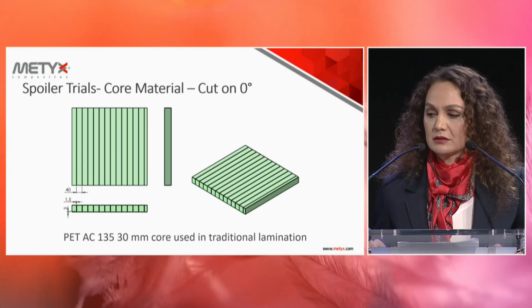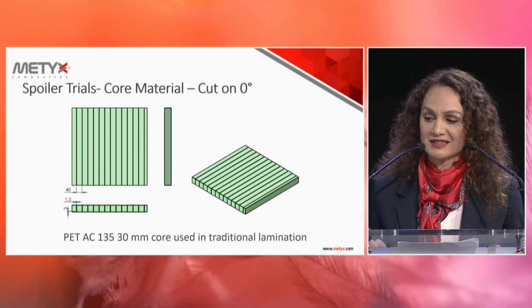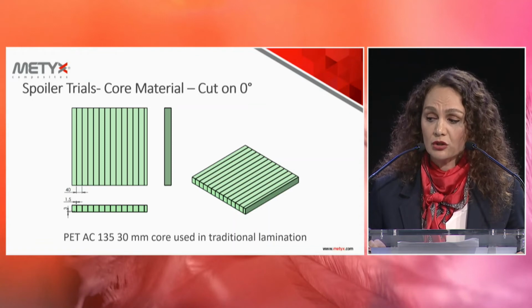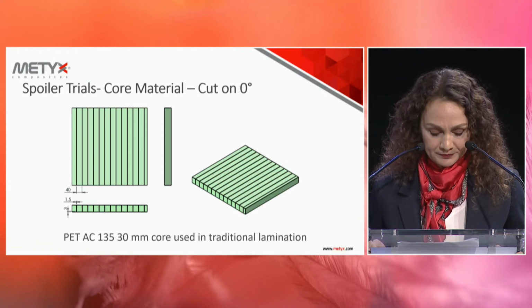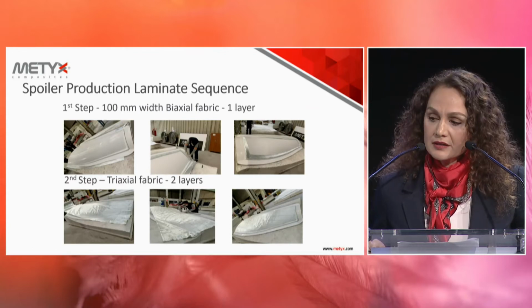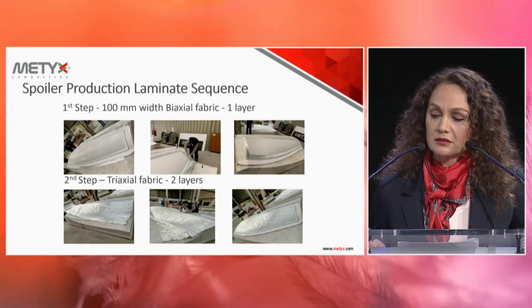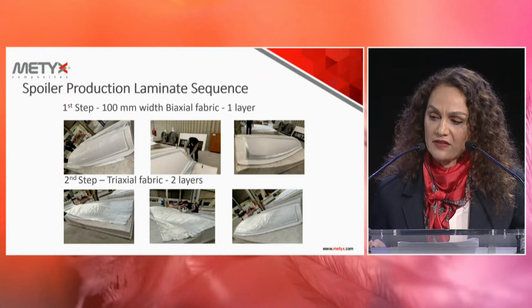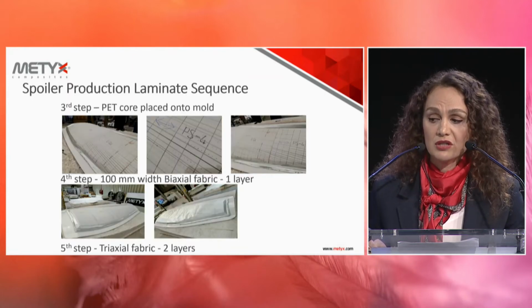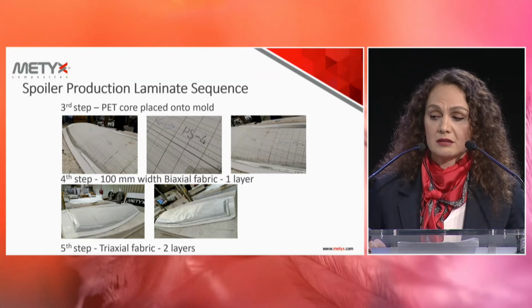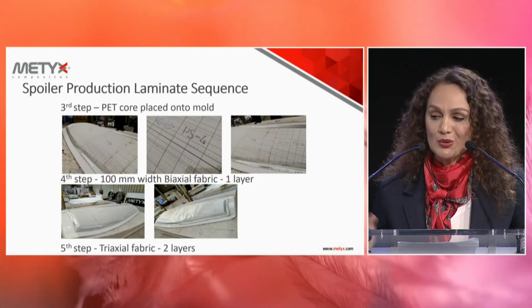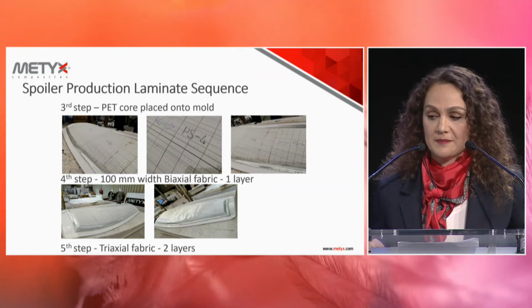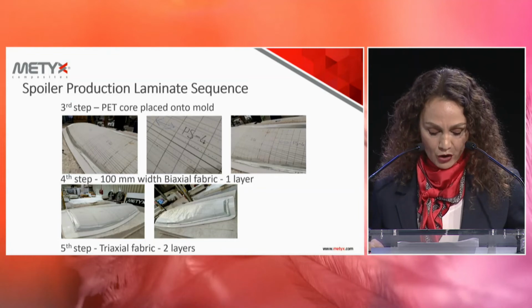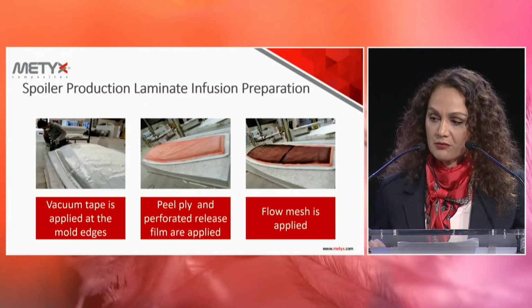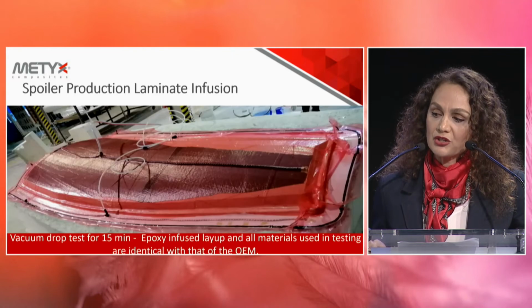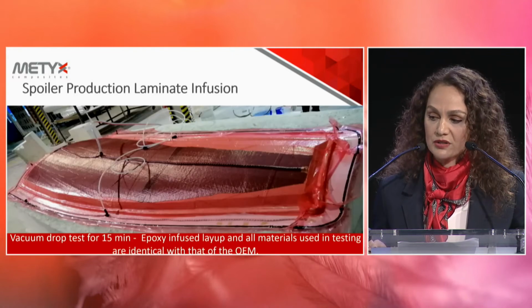So the other comparing core has the cuts in 0 direction. It has the grooves. So you can see the same laminate sequence in biaxial and triaxial fiber lay down. And then on the top 3 images, you can see the PET core. It has lots of grooves and cuts on it. We did not experience that in our thermoformed PET. Again, same infusion preparation, classical epoxy infusion.